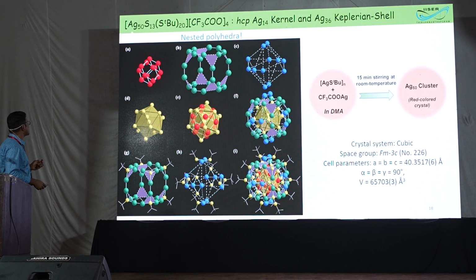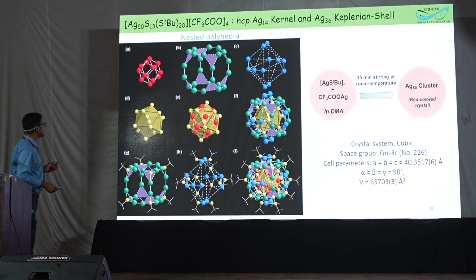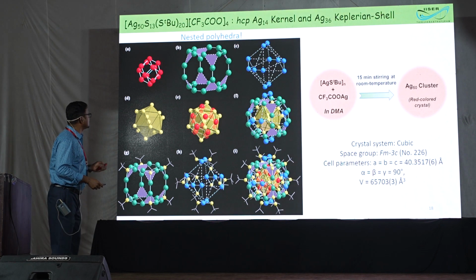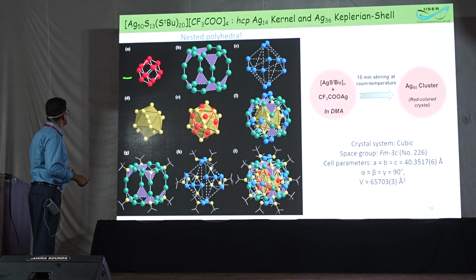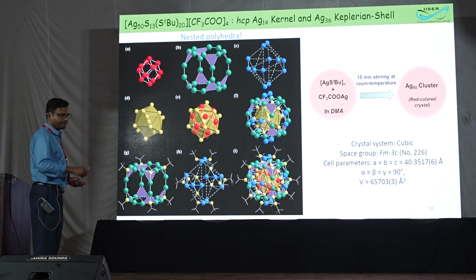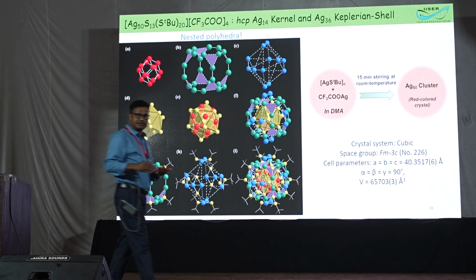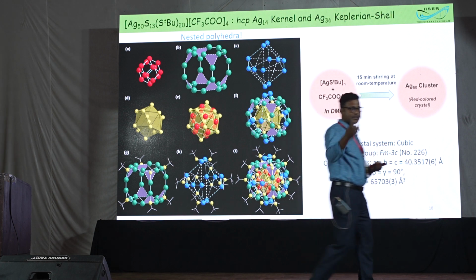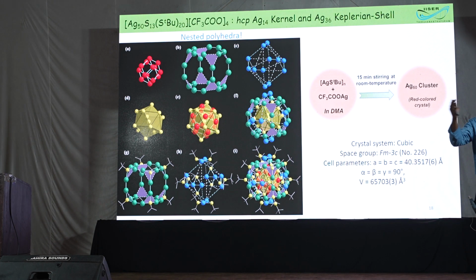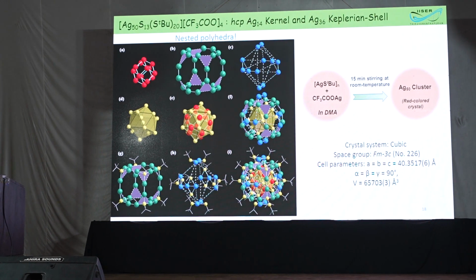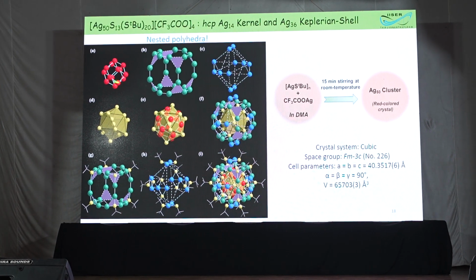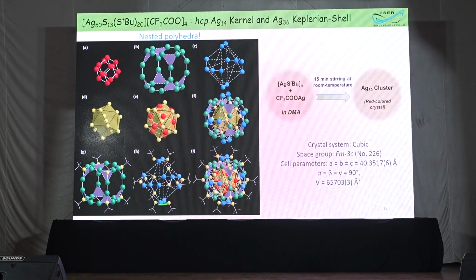We have synthesized the cluster of Ag50, which is protected by tertiary butyl thiol, and this is that. This is the Ag50 structure, this is Ag14. We know that A, B, C packing will be cubic close packing, because Professor Kulkarni has beautifully talked about how the FCC, non-FCC change happens. This is the 14 A, B stacking, this 24 is kind of a bowl, and this is the 12. This is the 50 silver nodes. This is the S13, 2 minus, that forms the icosahedron. Then if you blend with this, you can have the Keplerian cell structure.